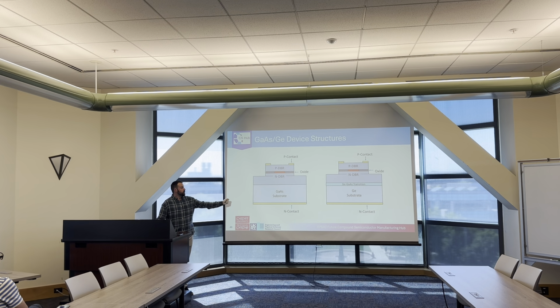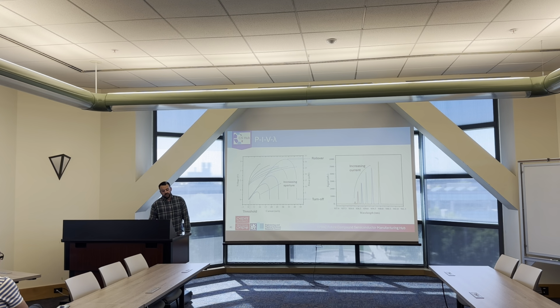Typical device structures, again, the only difference nominally is the germanium to gallium arsenide transition. We're going to look at the power, current, voltage, and optical spectra for both GaAs and germanium devices, extract threshold currents, rollover currents, peak power, and turn-off currents. Look at this as a function of oxide aperture, same for series resistance, and then the emission spectra, look at that as a function of current and temperature, and the IV as a function of temperature as well. Put all that together, compare the room temperature performance essentially, and also the thermal performance.